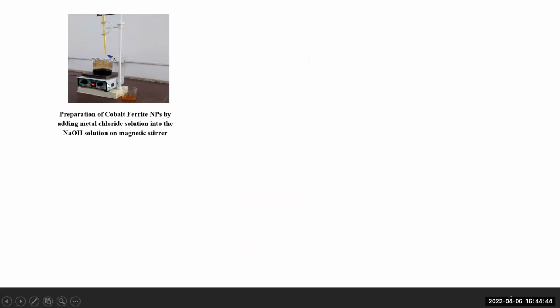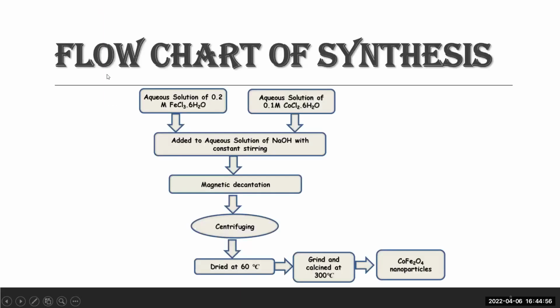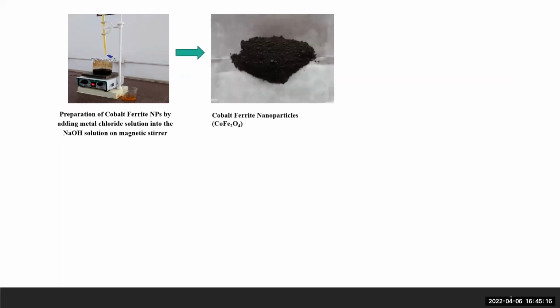You can see here in this picture the reaction, the complex mixture of ferric chloride and cobaltous chloride in this burette, and after the reaction we get the solution in dark brown color. And then we do the magnetic decantation, which was followed by centrifugation. After centrifugation, we got the sample in the form of precipitate, which was dried at 60 degrees centigrade, and followed by grinding and calcination at 300 degrees centigrade to get the cobalt ferrite nanoparticles. So we get the cobalt ferrite nanoparticles in the form of powder of dark brown color.